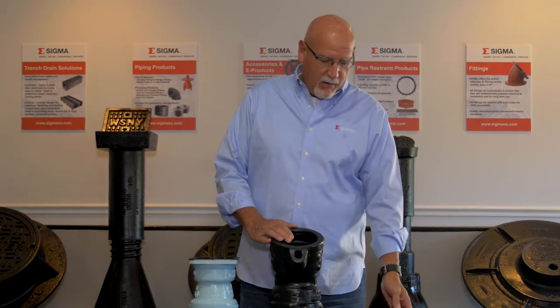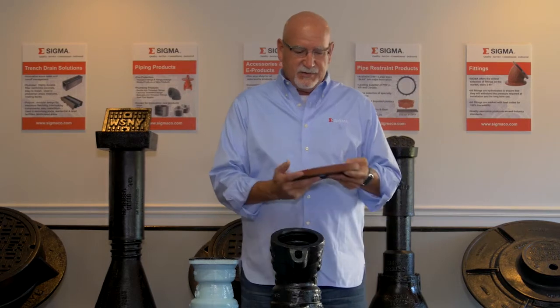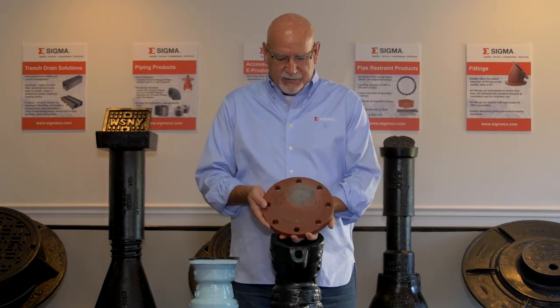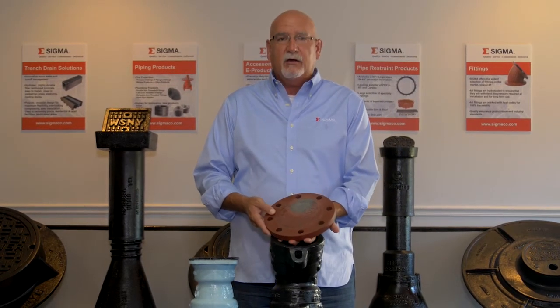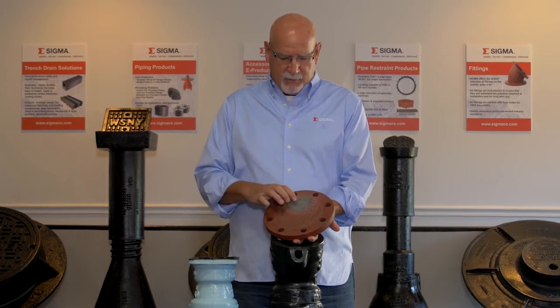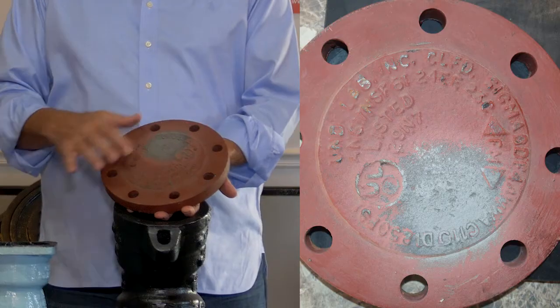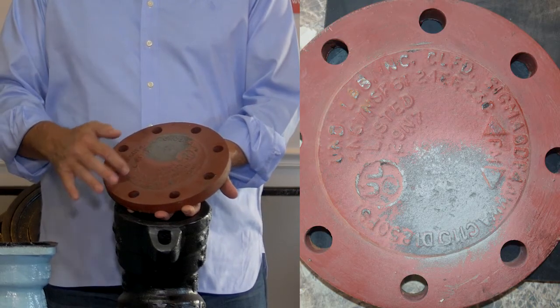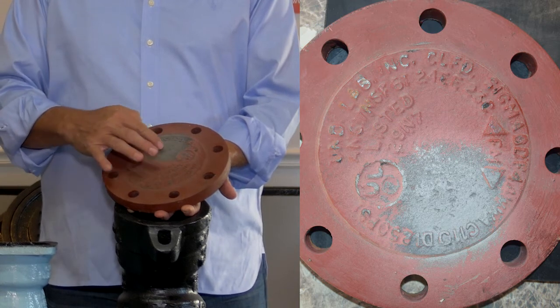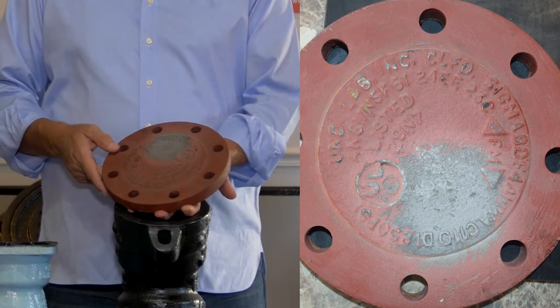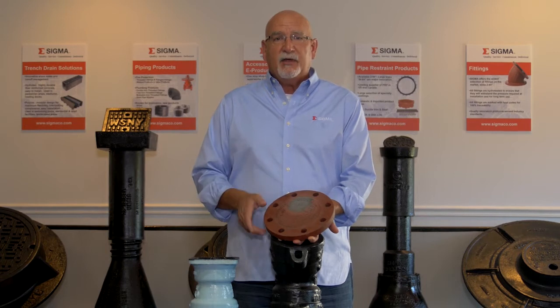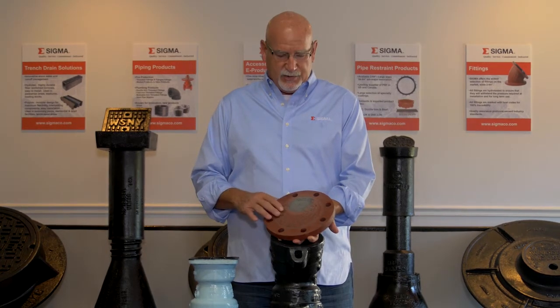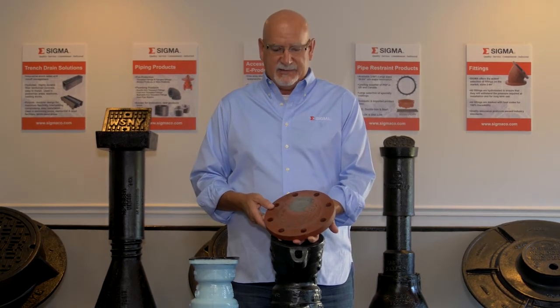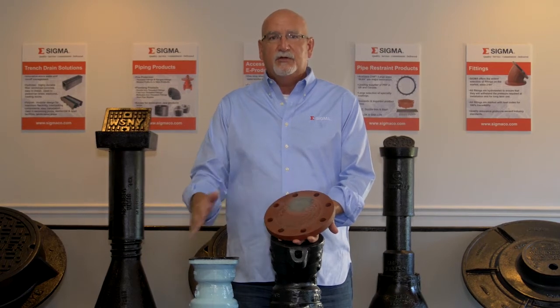So in all applications for coatings, a product should start at what's considered near white metal blast. You can see this small spot on this flange. This is a primer coat. We blasted off the primer to a near white metal blast. Suppliers of paint and paint systems will always encourage you to start with near white metal blast before you build up to the final coat.